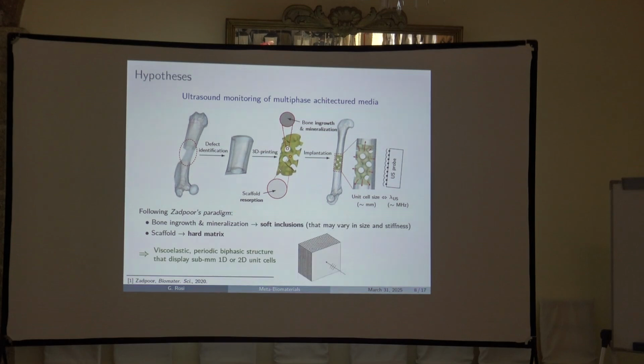And so we have to play with the viscoelastic periodic biphasic structure that displays sub-millimeter 1D or 2D cells. And something like this, basically. This will be the size of the specimen. We will have a plane wave arriving on this specimen where you have some kind of 15 or 20 unit cells in the specimen. There are basically two materials, one softer and one more rigid.